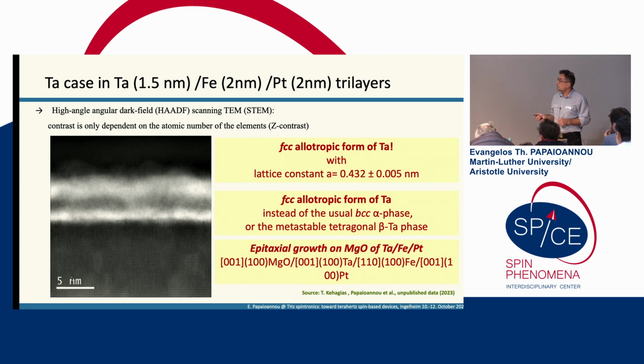So in this field, this is a high resolution electron microscopy image, where in principle the contrast depends only on the difference of the atomic number. We also have diffraction contrast images where we can see the very good epitaxial growth of tantalum on MgO, and then the iron and the platinum in this epitaxial relation. So tantalum grows epitaxially on MgO, iron rotates its lattice 45 degrees, and then platinum fits on top of iron.